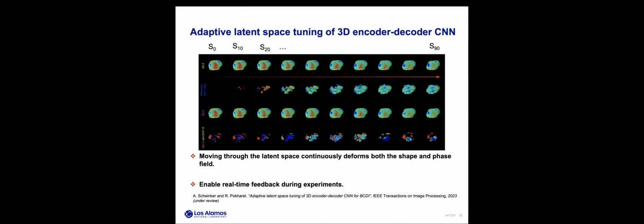So the implication of this result is that during an in-situ experiment, this approach can allow for real-time tracking of a grain evolution. And all of these right now are demonstrated only on simulated data, but we are collaborating with Ross Harder at Sector 34 IDC to extend these approaches for experimental data reconstructions.